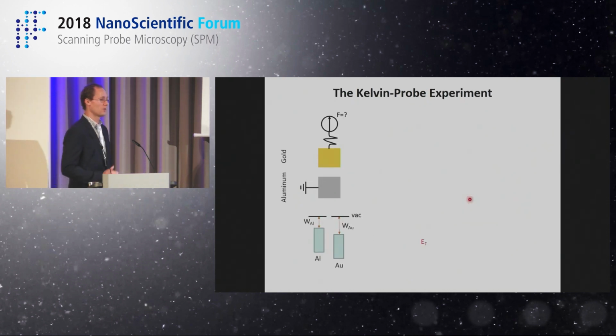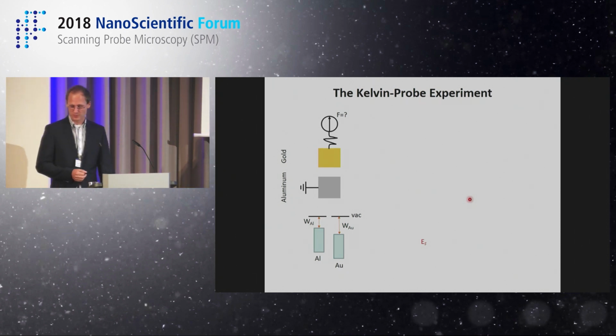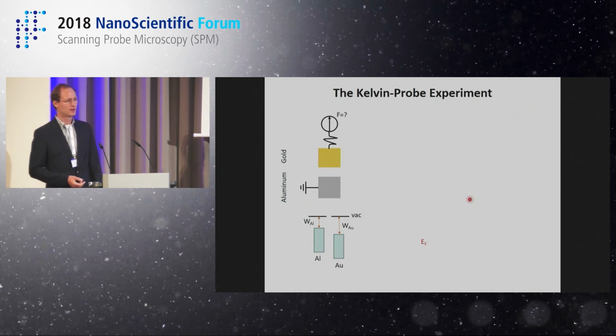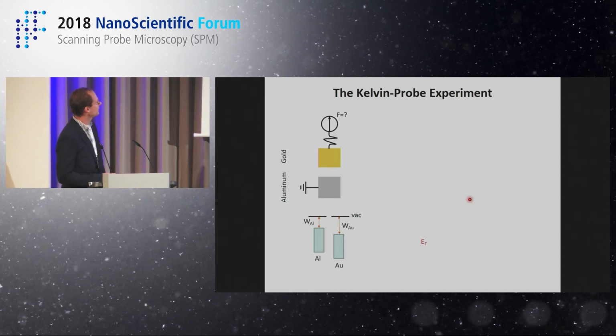to switch way back in time to macroscopic systems and look at the so-called Kelvin-Probe Experiment. It's not so intuitive, but let me just give you a brief introduction. In the Kelvin-Probe Experiment, what you basically do is you have two different metals. Let's just suppose we have, for example, gold and aluminum, okay? And we bring them in close contact, and we measure the forces that build up between the two of them.